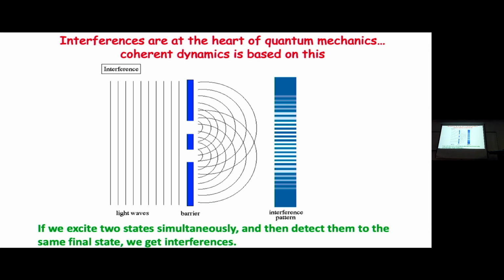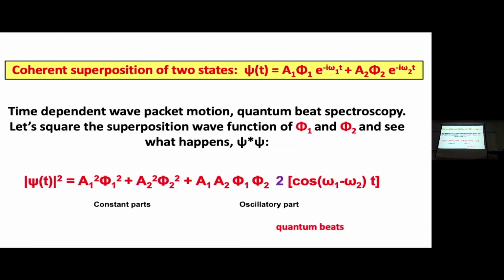So what is not as obvious is if we excite two states simultaneously and create a superposition and then detect them to the same final state, we also get interferences. So these two states have to be same energy? No, they're completely different energies. Yep. So the mathematics of that, in just a 2-second view, is we sum two wave functions like this, an amplitude, a wave function, and a frequency factor, the e to the minus i omega 1 t, with the other, and now we square it.